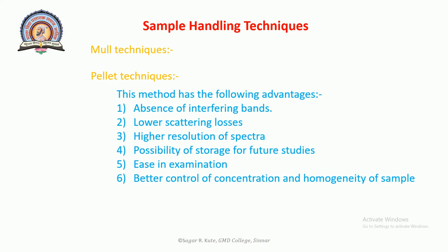Second will be the pellet technique. The first step in this method is to grind sample very finely with potassium bromide. The mixture then presents transparent pellet with the help of a suitable die. This is placed in IR beam in a suitable holder. This method has following advantages.